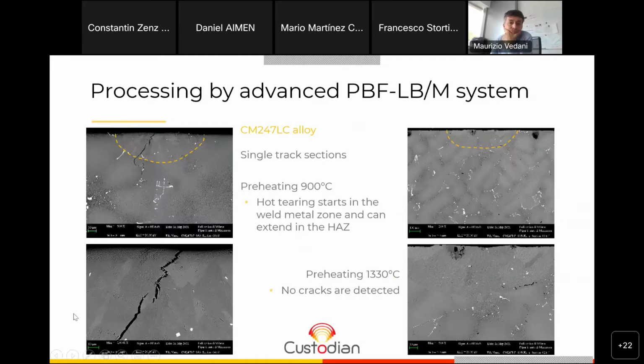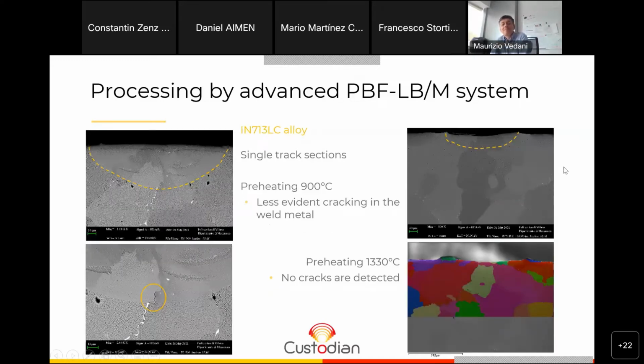And here you can see some of the samples that we got using this approach. As you can see on the left side, there is a CM247 low carbon block that was heated up to 900 degrees C. And in the SEM cross-section images that you can see, we can observe cracks that start in the weld metal zone and extend into the heat affected zone. However, if we look at the samples shown on the right side, they correspond to CM247 low carbon as well, but in this case the sample was heated up to around 1330 degrees C. We can clearly see that the cracks are not present. Thus, we can conclude that very high temperatures must be achieved if we want to get rid of cracks. And Mauricio, if you pass to the next slide, the same behavior for Inconel 713 was observed.